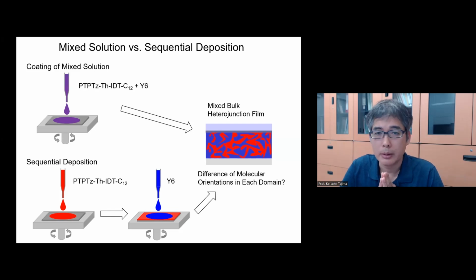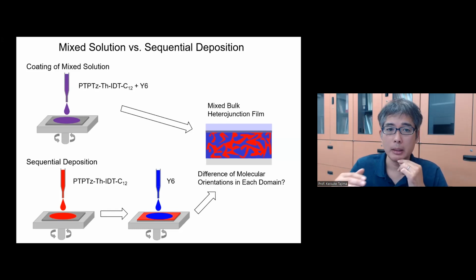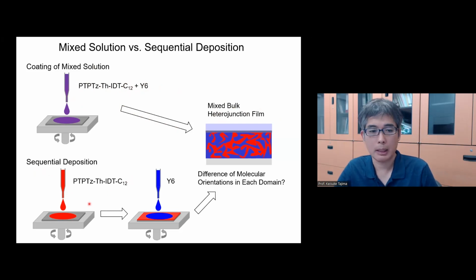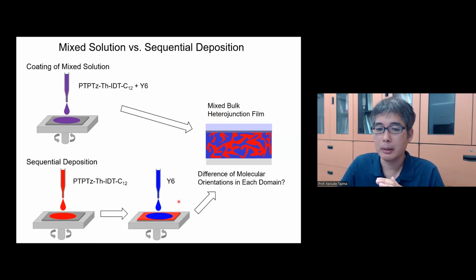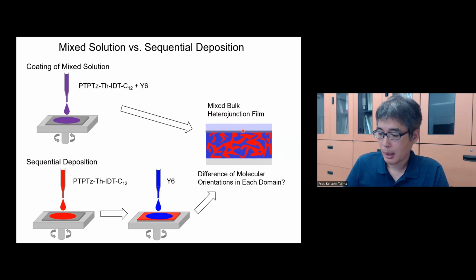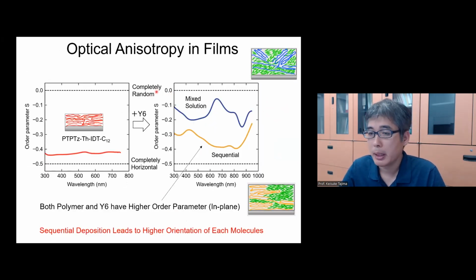Another thing we can do to control the molecular orientation is how to make the film. We can modify that. Usually, the bulk heterojunction film is just a spin coating of a mixed two components, the polymer donor and acceptor molecules, spin coated on top of the substrate. This is the ordinary way. But recently it's getting popular to use this sequential deposition method. That is, the polymer is deposited first and dried, and then you spin coat this acceptor molecule on top of it. And then these Y6 acceptor molecules diffuse into the polymer film very well. So the resulting structure is close to this mixed bulk heterojunction film. But the question is whether this process gives the same structure, or is there any difference, particularly in the molecular orientation in each domain? That is our question, and we tried this optical ellipsometry again.